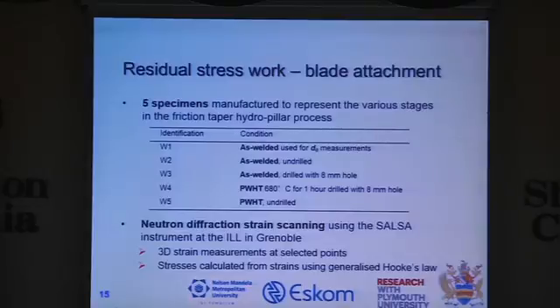This is what we've done with the residual stress part. We've welded 5 samples, 3 of them as welded. The first one we cut up into D0 samples. The second one we left undrilled. The third one we drilled an 8mm hole through. Then we had 2 samples that we did post-weld heat treatment on, one drilled, one undrilled. Remember, you've got a week of beam time and you have to get all of this data through, so you rather take fewer samples than more, but make sure that your data is valid.